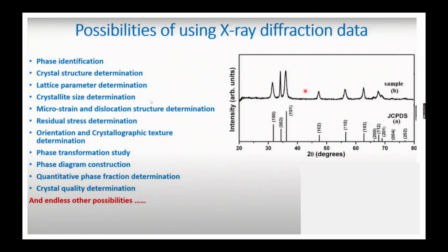Yeah. So this is about the possibilities: suppose I give you XRD diffraction data, what can you extract, identify and determine from that data? The first thing is phase. We can also get the crystal structure, as we have seen in past lectures, whether it is FCC, BCC or SCC. For that I have also shown the criteria and how we can determine it, with rules for H plus K plus L in each type of crystal structure. Then lattice parameter determination, crystallite size determination, just a few slides back, microstrain and the dislocation structure. We can also determine the effect of peak broadening that can be caused by strain. Residual stress determination, and orientation and crystallographic texture determination, we can also do.